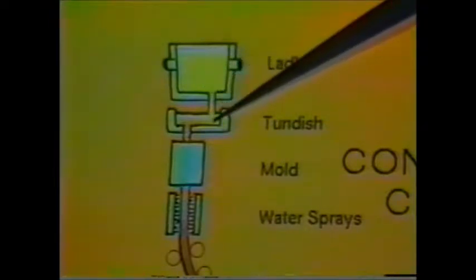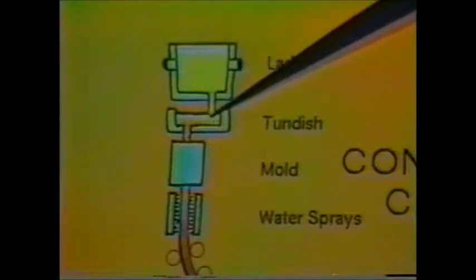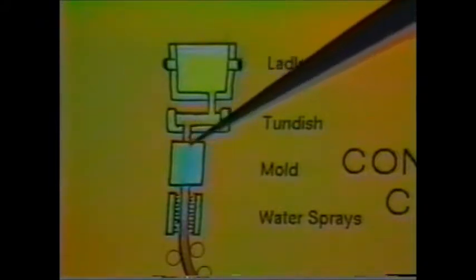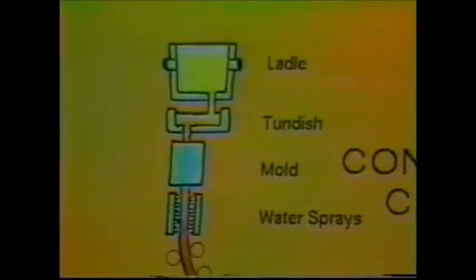of the casting sequence. The molten steel is released from a ladle into an intermediate container called a tundish, then into the mold. Control valves, called gates, in the ladle and tundish allow the levels of molten metal to be held constant in the tundish and mold. And because the mold continuously empties as it's being filled from the tundish, one strand cast mold can do the job of many ingot molds.